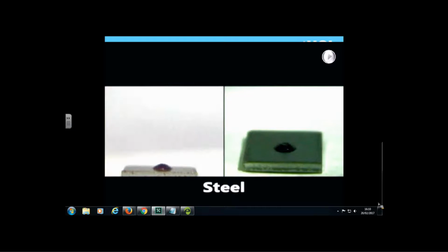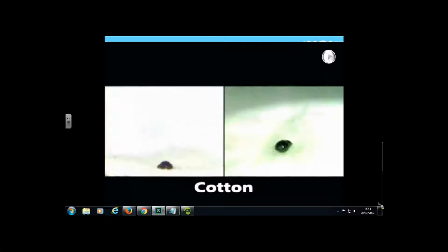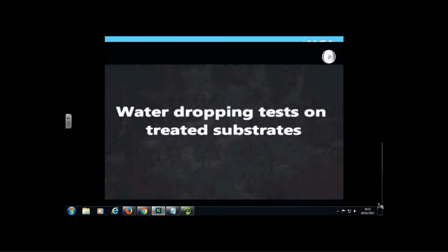So this is our coatings which have not been treated with a superhydrophobic surface. I'm dropping water droplets onto cotton, paper, steel surfaces, and you see that the water droplet just splats onto the surface.